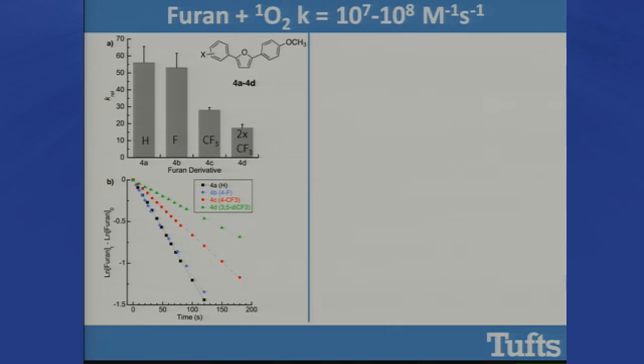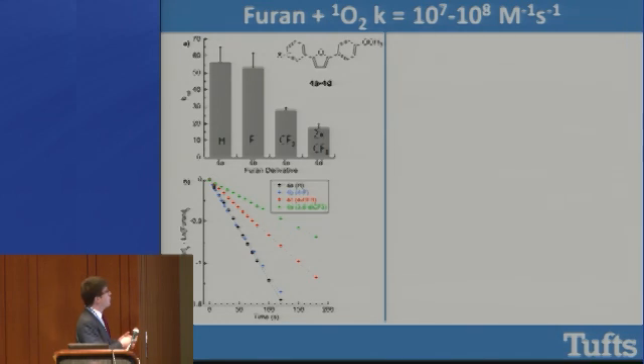And so what you're looking at here is the pseudo-first-order rate of these compounds, and here what I'm showing you is the different substituents that we put on this diaryl furan. We look at the rate of disappearance of it upon exposure to singlet oxygen as a function of structure. And as you might expect, as we make this furan more electron poor by putting on electronegative fluorine atoms, we decrease the rate of cycloaddition significantly. All of these reactions follow pseudo-first-order rate laws because we're keeping the concentration of singlet oxygen at a steady state under these photosensitization conditions.